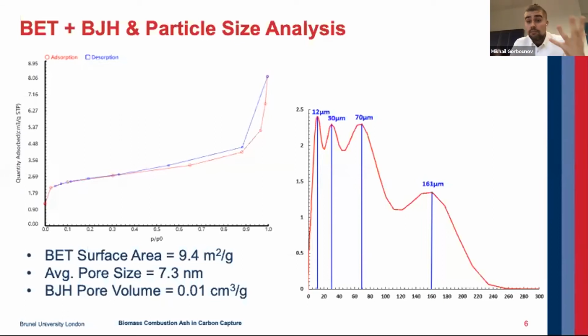Considering these suggestions from both of these pathways, as well as the manual measurements of the SEM images, our conclusion is that the phase is not homogeneous, though the bulk of the material is present in the form of glassy spheres of various sizes. The mineral phases possess a non-spherical geometry, though their particle sizes generally fall within the range of the main peaks described on the slide.